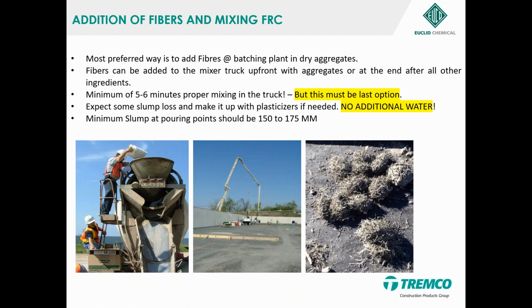So a lot of people will have doubts about adding fibers. The most important thing we would want to practice is to add the fibers to the dry aggregates as much as possible. I would say we should not compromise on this, because a lot of fibers are fibrillated or fibrillating. There are two different words in this. So it is better that once it has gone into the friction between the 10 mm, 20 mm and sand, the fibrillation happens, it opens up, and it has a better anchoring into the concrete when it opens up. So it is better that we add these fibers in the dry state.